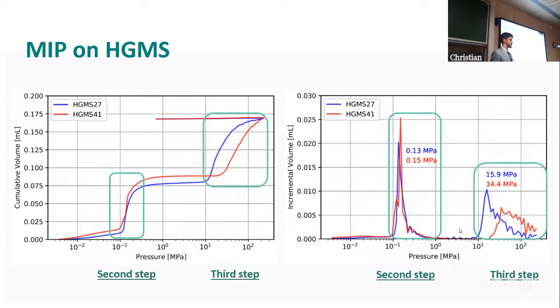Not more than that. Then for the red one, which in this case is the HGMS41, the one that is stronger, the main peak occurs at around 35 megapascals. So I will go between 5 and 10 megapascals less. So I will go between 20, 25, 30 megapascals in that range. With that, I will be more or less safe that I'm not breaking them. But to properly say this, I have to measure to what extent the outer shell is affected. I don't know if with this I answered the question.